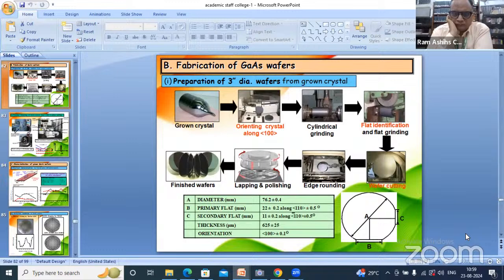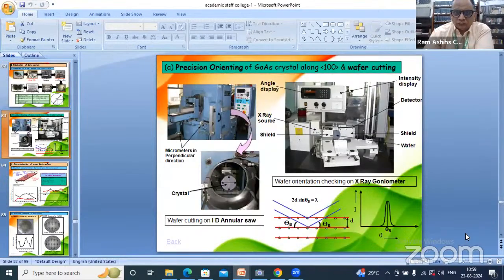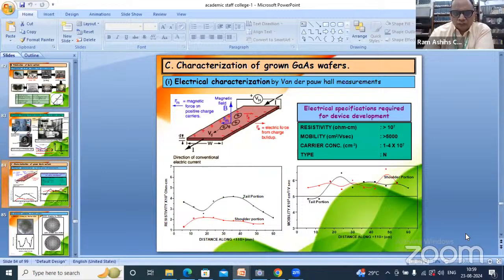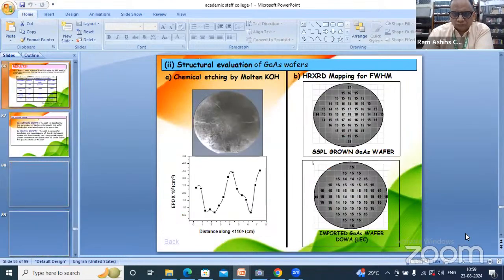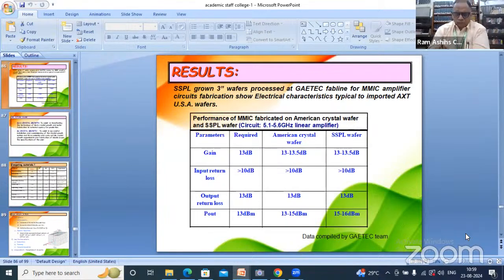By orientation with the X-ray goniometer, in the 110 plane, we do cylindrical grinding and flat orientation, flat identification, and flat grinding. Then wafer cutting, edge rounding, and lapping and polishing, and then the finished wafer for further use. This is the precision orientation of gallium arsenide crystals along with wafer cutting. Some other department is doing characterization and giving results to us. These are the various characterization results. This is the comparison with American crystal wafer. It is more compatible with our SSPL wafers.